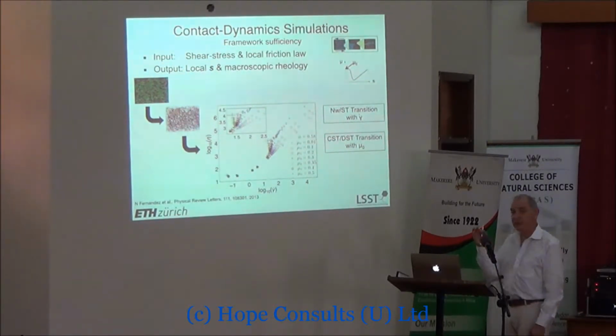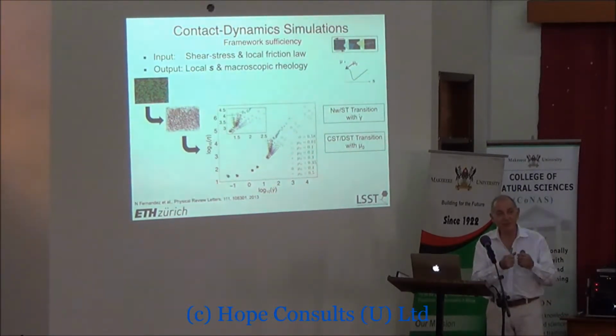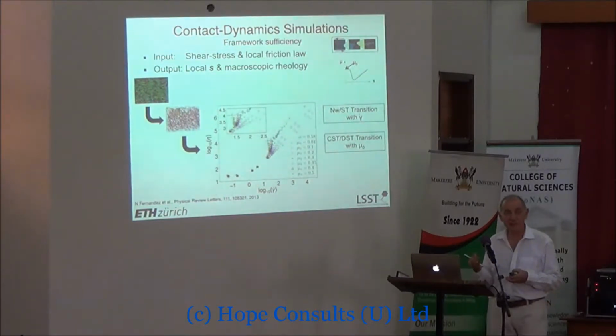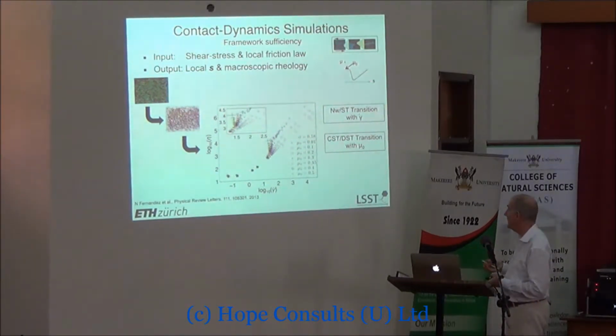So it seems like if you lower the friction coefficient between these two cement particles when they collide with each other, then you can avoid getting into the discontinuous shear thickening. So this is very promising because it seems like just by adding a polymer that will lower the friction on the surface of these grains, we could cause the cement slurry to behave in a more well-behaved way.